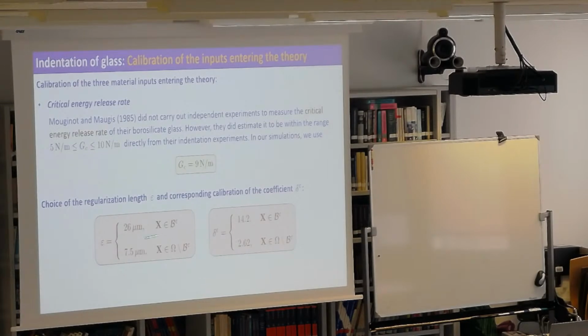So because we have different strengths in the layer with the abrasion and in the bulk, we wanted to have the same epsilon throughout the entire solution. So that's why if we change the epsilon, we actually change the thickness of the phase field crack when you change delta epsilon. And that's why we have 2 different epsilons, right? It's the reason. Okay. All right. So in the solutions that I'll show you, again, epsilon can be this or you can make it smaller. It doesn't matter. The solution is the same. It's epsilon independent, at least numerically, right? It's really truly independent of epsilon.